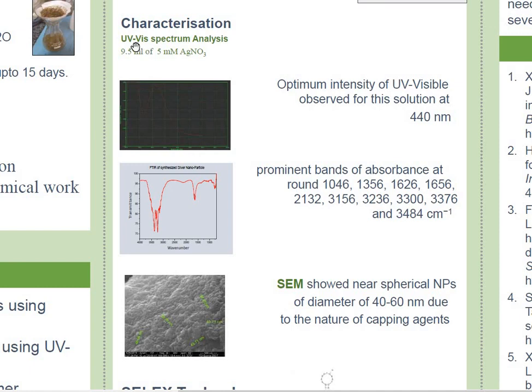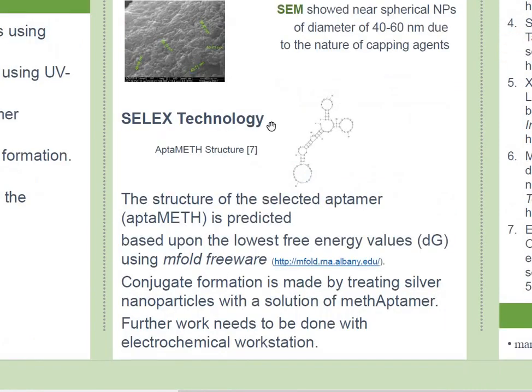Then under characterization, UV-Vis was used. This showed a prominent peak over here at around 440 nanometers for this particular solution. FTIR showed prominent peaks at around these, and SEM also showed the presence of silver nanoparticles of diameter 40 to 60 nanometers. Then SELEX technology was used.